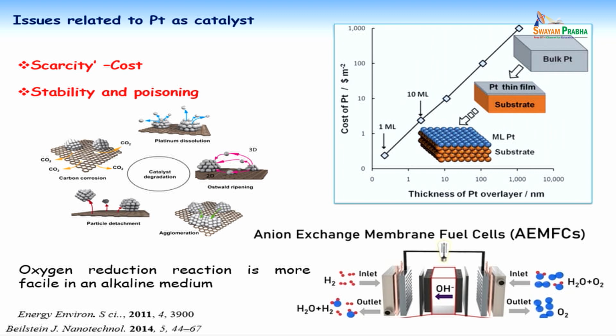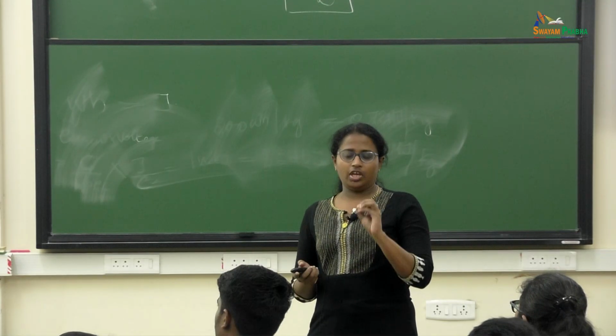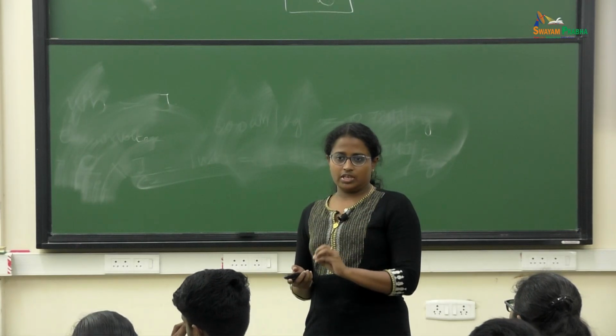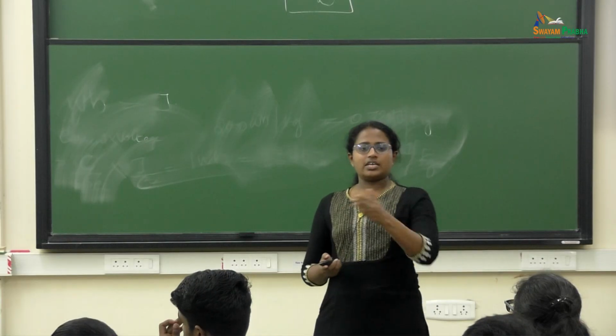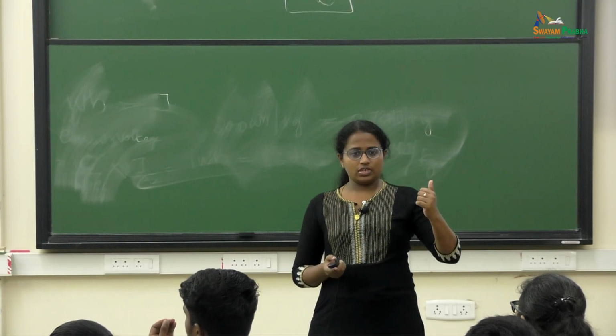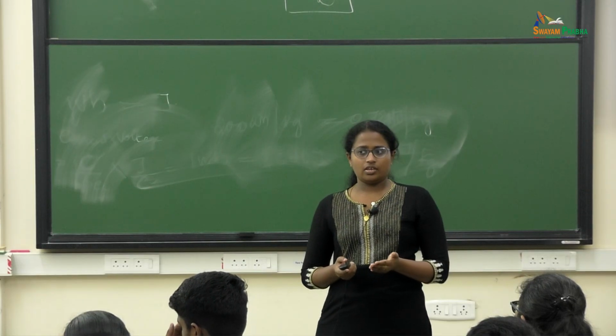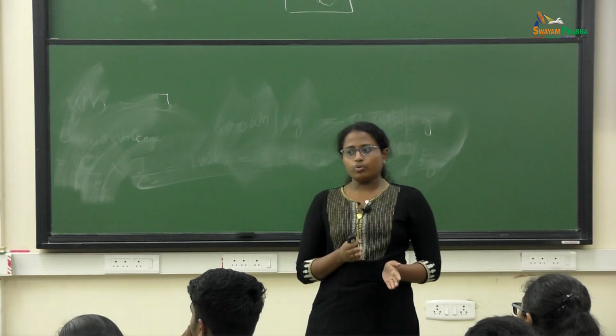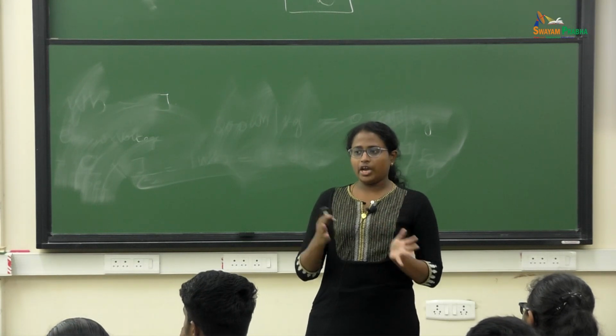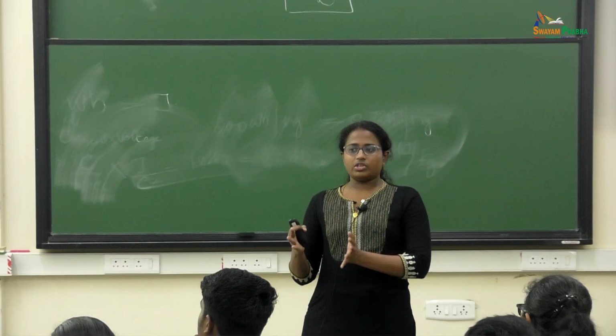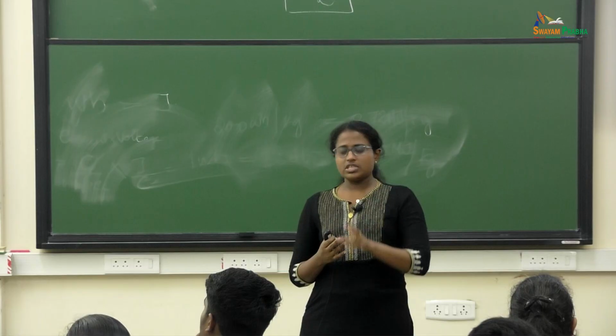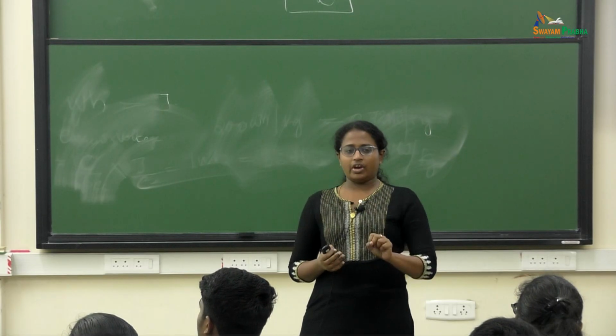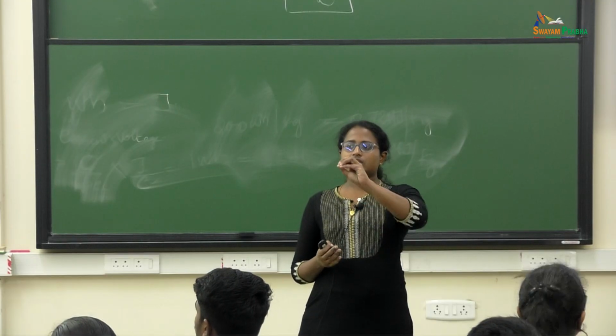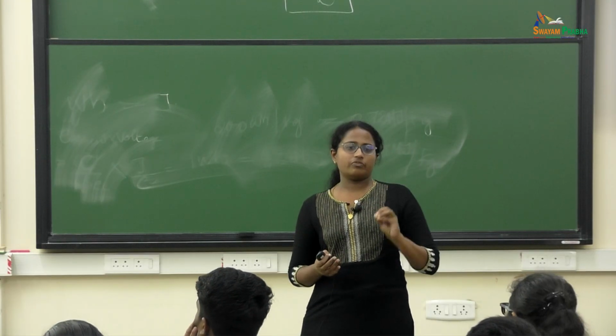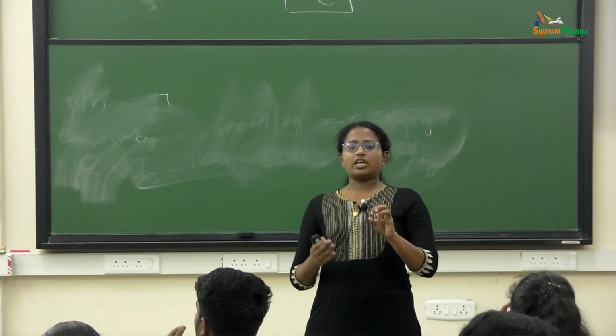But again, platinum is prone to surface poisoning. Actually, if you have a very low amount of carbon monoxide or carbon dioxide in the hydrogen gas, for example, he was asking what is the hydrogen cost. So, for example, if I use refinery hydrogen, actually produced by processing crude. Crude contains hydrocarbons, right. So, it will contain a lot of impurities like carbon dioxide and carbon monoxide. If I use the same hydrogen from the refinery as a fuel, what happens is that this carbon monoxide or carbon dioxide can poison the surface of the platinum. It will adsorb onto the surface of the platinum very strongly.